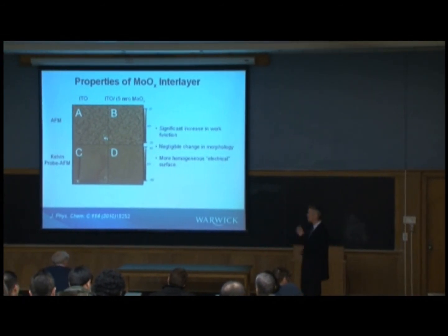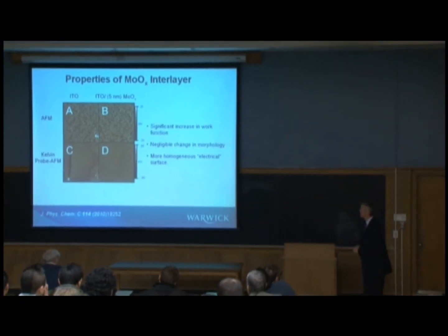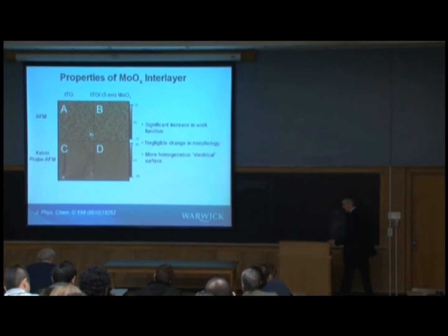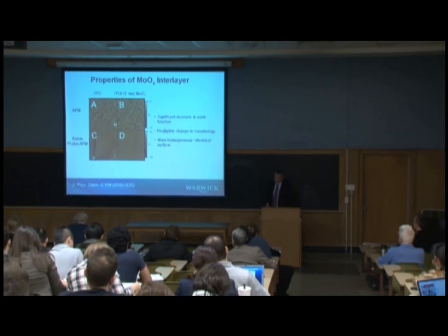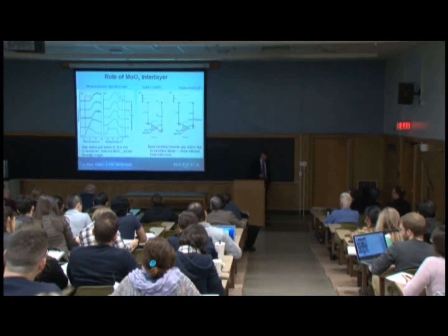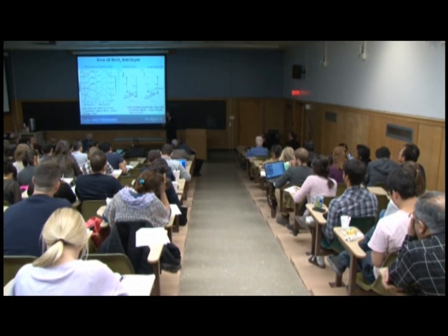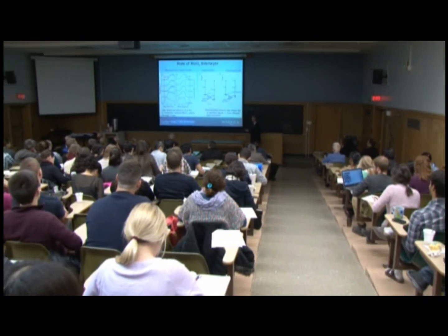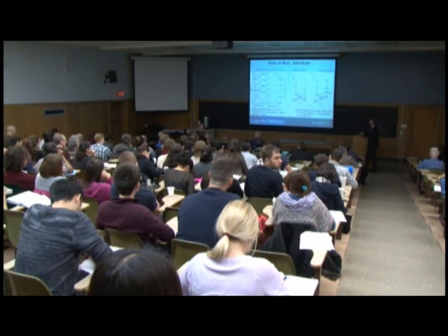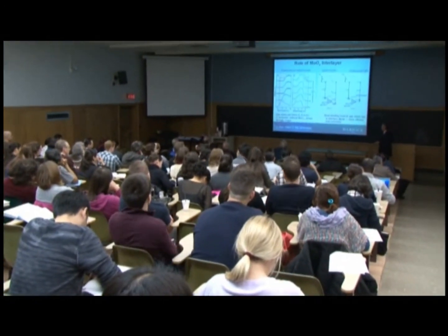Remember, I said that ITO is one of the limitations in the performance of these devices. So it's not a morphological effect, but there are some significant changes in electronic properties. And in fact, one of the key points can be seen in the photoemission of the molybdenum oxide. So these are, again, photoemission results as a function of molybdenum oxide thickness up to about 20 nanometers. Again, looking at the shifts in the work function as you go from bare ITO to a molybdenum oxide coated film. And then the valence band structure shown here.